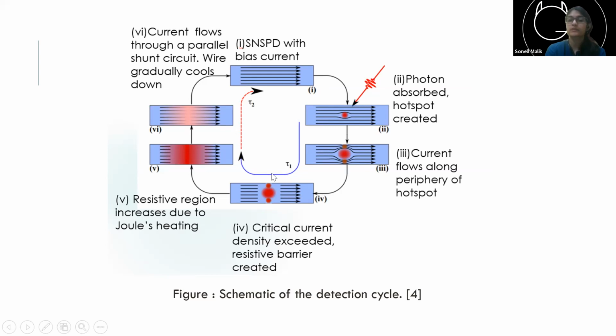Tau 1 takes about, I think, a few picoseconds. This doesn't take very long: the photon is absorbed and then the heat quickly spreads. Tau 2 is what we call the dead time, and that could range depending on how good your SNSPD is, how thick your thin film is. This is also where the thickness of your SNSPD matters, because of how the energy dissipates. The electrons are basically heated. When this hotspot is created, in this region the Cooper pairs will break down, and these electrons will now have a very high energy and go about everywhere, heating everything up.